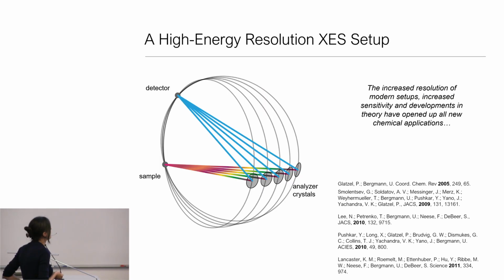There's been increasing interest in the last, I would say, 15 years or so in high energy resolution X-ray emission setups that increase the intrinsic resolution by using a Bragg optic. In a sense, we're doing the same thing that we do with our upstream monochromator. But now instead of sending the fluorescent signal from our sample to our low resolution detector, we first send it to a Bragg optic to spectrally analyze that fluorescence, and then we send it to our detector. By doing this, we can get much higher resolution, and I'll show you a little later exactly how that works. But let's first talk about why we would do this and the kinds of information we get out.